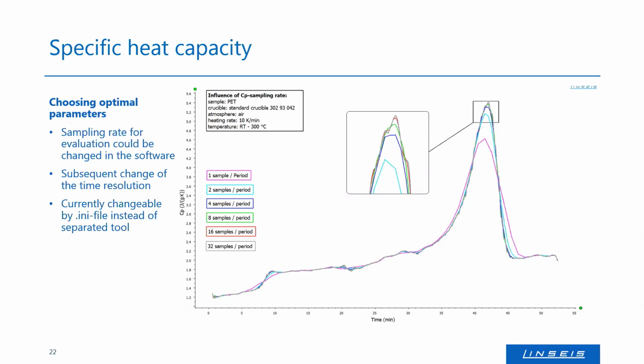So if you're just interested in the measurement without any glass transitions or transitions at all, then it's totally okay to choose fewer samples per period, so a lower sampling interval. But if you're interested in the glass transition or something like this, then you should choose a higher sampling rate here. As you can see, the glass transition with the gray measurement here, by the way, it's the same measurement, is much sharper.